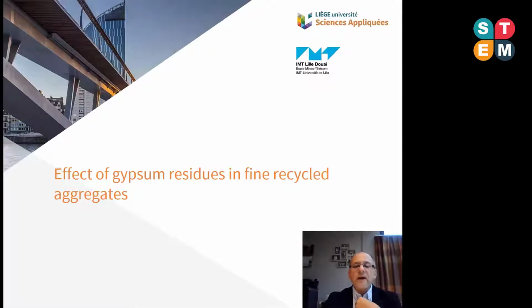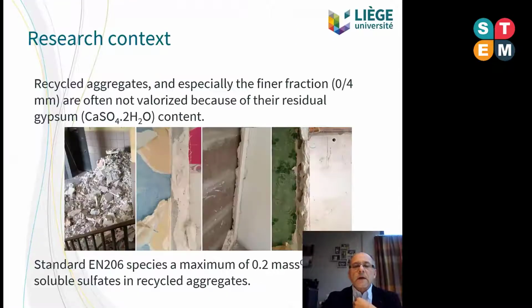So first of all, what is the effect of gypsum residues in fine recycled aggregates? Recycled aggregates, and specifically the finer fraction, that means the 0 to 4 millimeters, the sandy particles, are very often not valorized because they correspond to a high quantity of residual gypsum. Gypsum comes from the plaster used in buildings, and gypsum is characterized by a chemical composition of CaSO4·2H2O, which can be detrimental in the reuse and the valorization of this type of material.